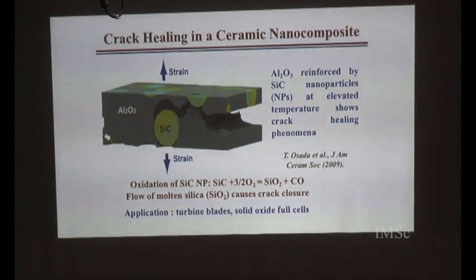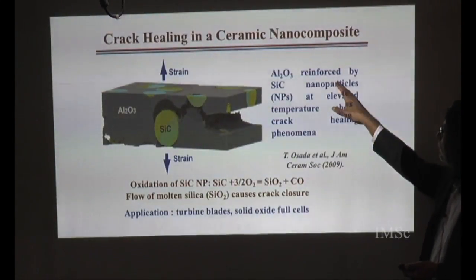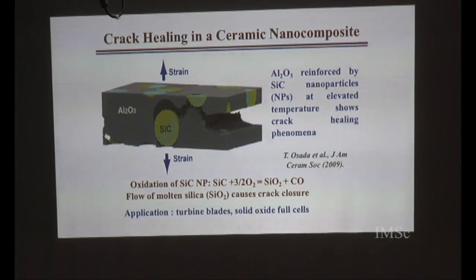But there were experiments done in Japan, and what they did was they embedded silicon carbide nanoparticles inside alumina, and they studied the mechanical response of this system to strains and so on. This was studied at sufficiently high temperature. So what happens there is that first silicon carbide oxidizes, so then you have a formation of an oxide layer on silicon carbide nanoparticles. And this is the chemical reaction. And what they found is that when cracks are formed and so on, they're also healed in the system. So when they do post-mortem on these systems, they find that the cracks have healed. And so we wanted to understand what is the mechanism of all that.